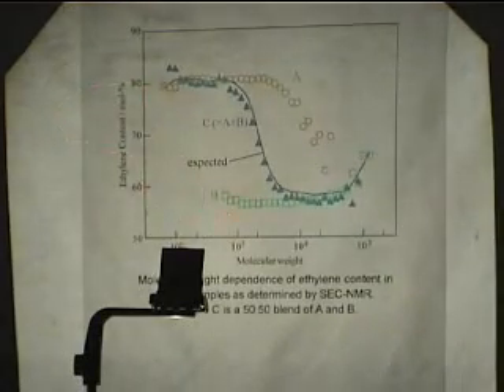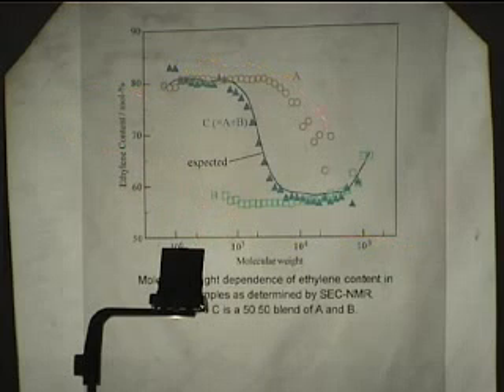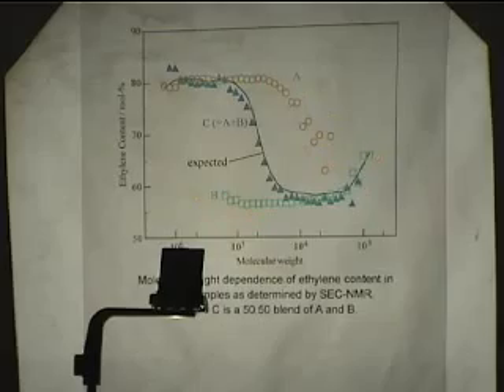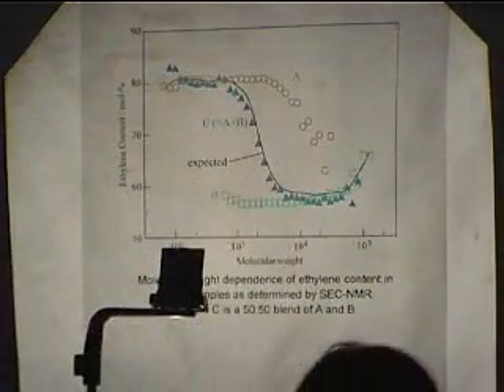We determined the ethylene content as a function of molecular weight for samples A, B, and the test sample C. The solid curve is the expected curve calculated from the results of samples A and B. As you see here, the plot for sample C agrees well with the expected curve. So this demonstrates the reliability of SEC-NMR for quantitative analysis.